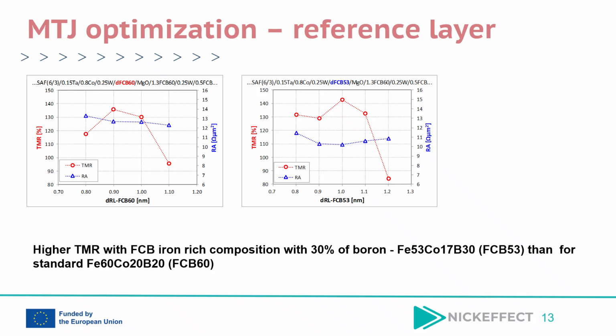The graph on the right shows the corresponding optimization performed for the FCB53 reference layer. In this case, even higher TMR values exceeding 140% were achieved for RL thicknesses around 1 nanometer, while simultaneously maintaining lower RA values compared to the standard FCB60 reference layer. These results indicate that the iron-rich FCB53 composition enables simultaneous improvement of both TMR and RA characteristics compared to the standard FCB60 reference layer.